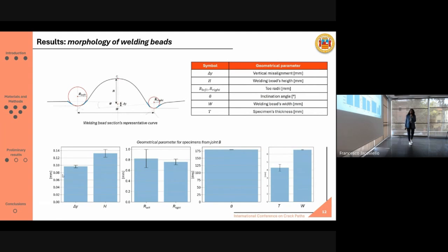Now, going on to the results, we have the first results regarding the morphology of the welding bead. So I reported here again the curve that represents the section of the welding bead and the main geometrical parameters. For the sake of brevity, I'm showing you just the geometrical parameters for the specimens from joint B, and in particular, these parameters are for the upper curve. We may see how the most scattered parameters are the two radii of the welding bead, so the left and right one, and even the height of the welding bead, and this result is quite expectable.